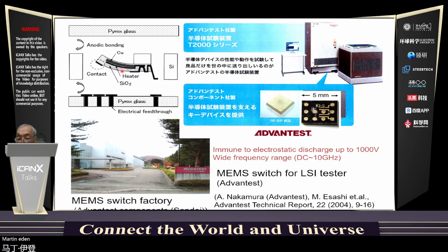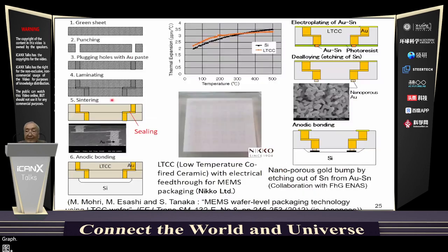Direct electrical feed through in the glass is required to minimize stray capacitance. However, there can be air leakage at the feed through because the metal of the feed through has larger thermal expansion than glass. We developed the electrical feed through using low temperature co-fired ceramics, LTCC, instead of the glass. The LTCC used has close thermal expansion to silicon, as shown in the upper center.